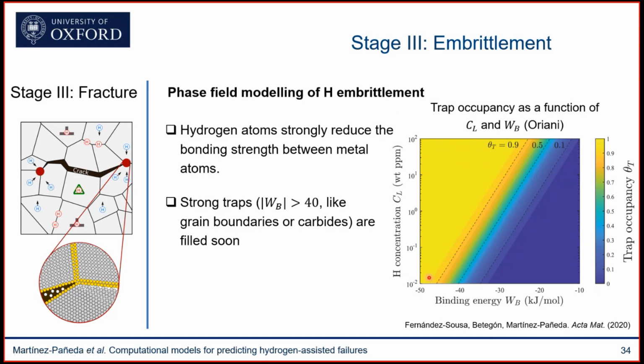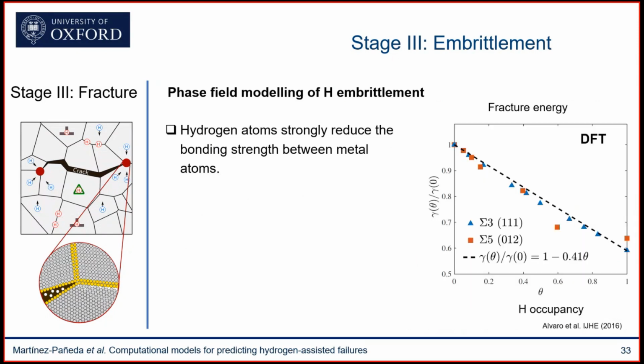This is what you're seeing here. So this is hydrogen concentration, binding energy, and trap occupancy. And we know, and we can measure in our lab, the binding energy for grain boundaries. And we know that this is higher or smaller than -40. So we are somewhere here. And we can see very easily that my grain boundaries are effectively going to be full of hydrogen for hydrogen concentrations as little as 0.2 ppm or something along those lines. So for very low hydrogen contents, we're already seeing that it is very energetically favorable for my grain boundaries to be full of hydrogen. So if I go back to the atomistic calculation, I know that I'm going to be somewhere here, and therefore we're going to have a very significant reduction of fracture energy.